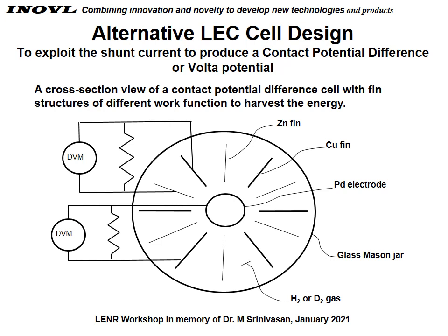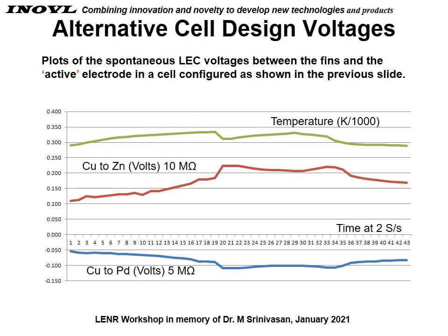We had DMMs going across between a zinc fin and a copper fin. We also had a DMM going from the palladium cathode to a copper fin. Here's an example of the LEC voltages between the fins and the active electrode in the cell configured as shown in the previous slide.